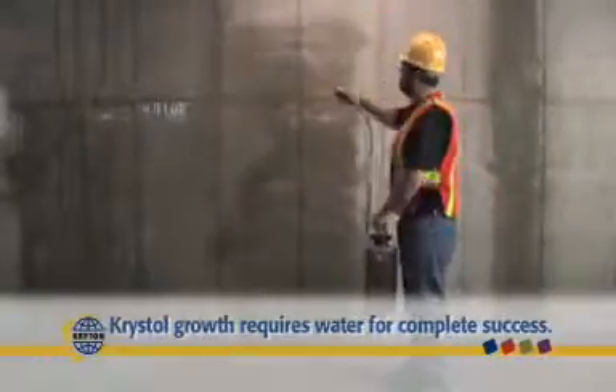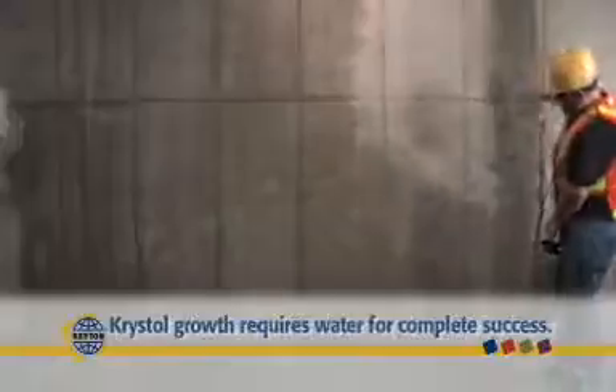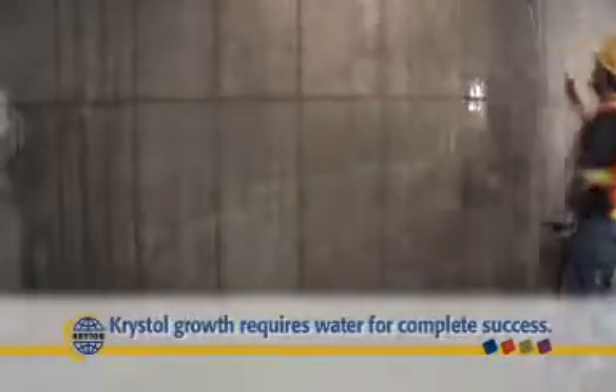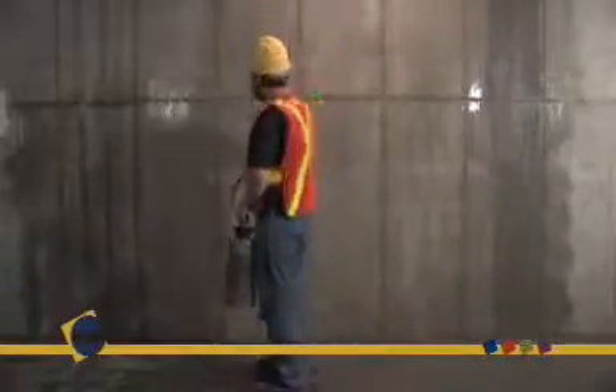Wet the concrete with clean potable water. It is important to pre-wet the substrate to a surface saturated dry, or SSD, condition, leaving no standing water. This is an important step to ensure that Krystol growth penetrates deeply into the concrete.